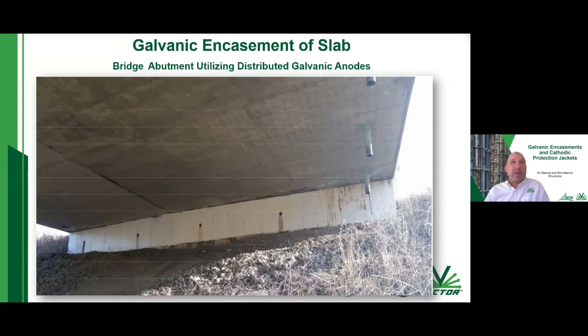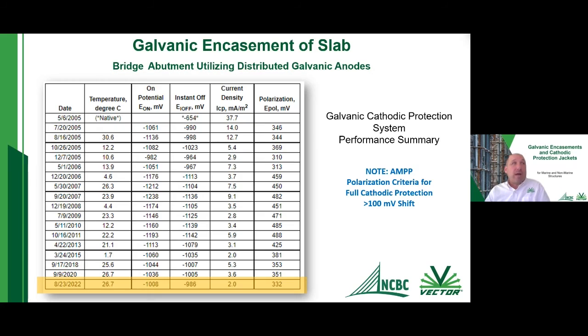And just another picture. This was, I believe, taken in, I'm trying to remember if it was 2022. But in this graph, what we're showing is, in order to get cathodic protection, look at the very far right column, our polarization. For NACE or AMPP criteria, you want to have at least a minimum of 100 millivolt shift. And what we're seeing here is much, much more than 100 millivolt shift in terms of CP for this abutment.